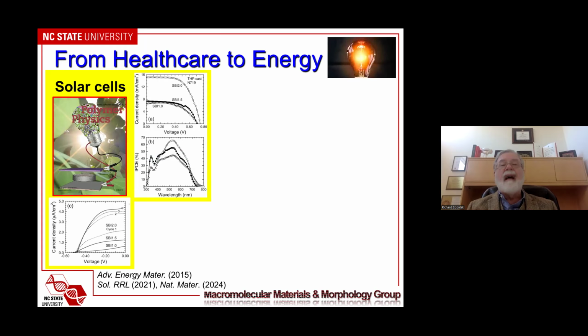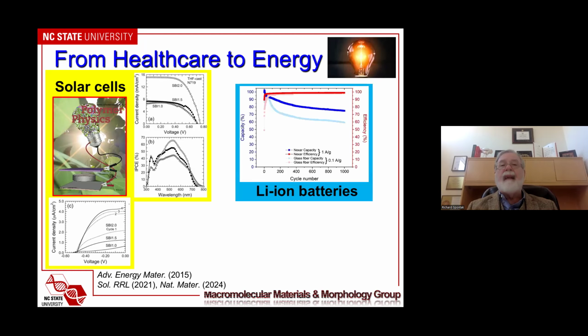So these materials have a lot of promise, and they're their own adhesives. So we don't have to start putting in additional components to these materials. And recall, they're thermoplastic elastomers. They are flexible. We can make batteries out of these, and we have lithium-ion batteries, where the material that I've been talking about is used as a separator, and we find that we can get, after 1,000 cycles, so this is about roughly 4 years of use, we can still get efficiencies that are close to 100% and capacities that are about 75%. This is on par with some of the best lithium-ion batteries out there. And again, this is not optimized. And we, again, rely on transport through those amphiphilic channels that I showed you in the TEM and tomography images.